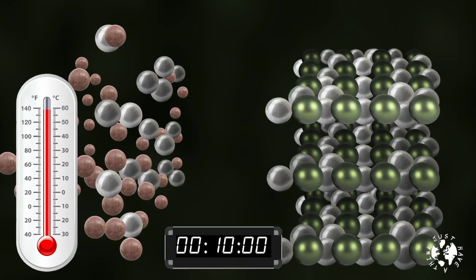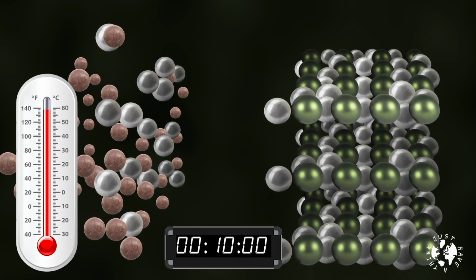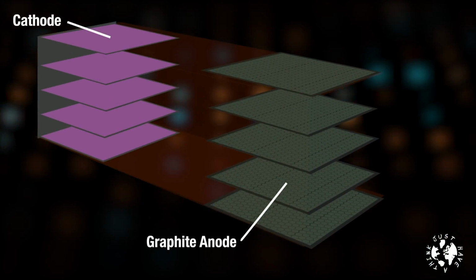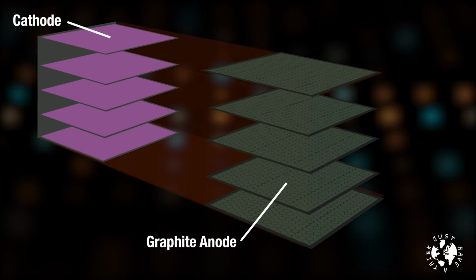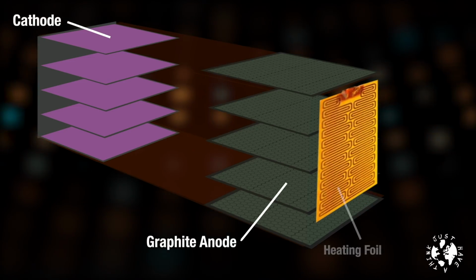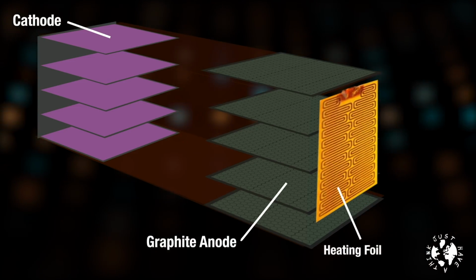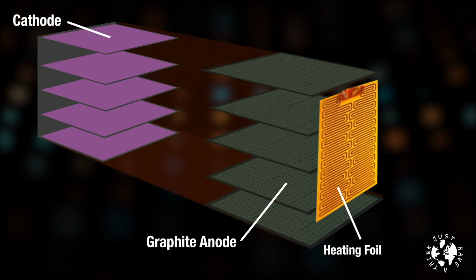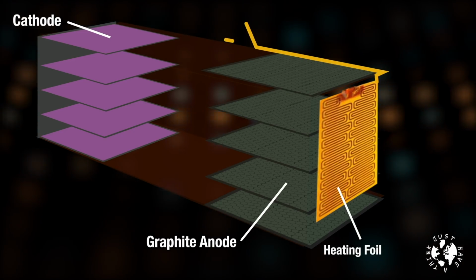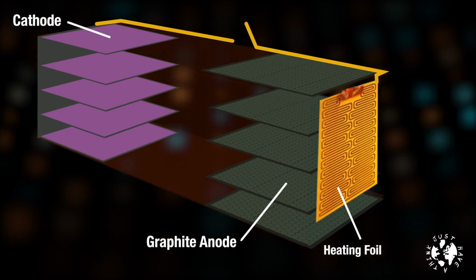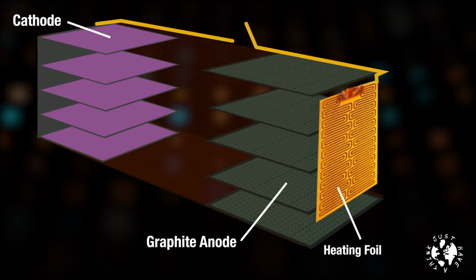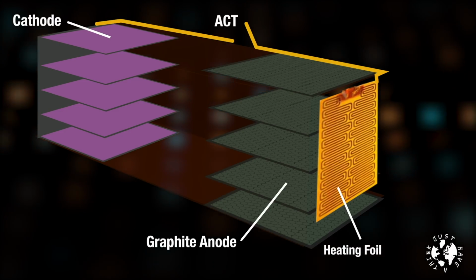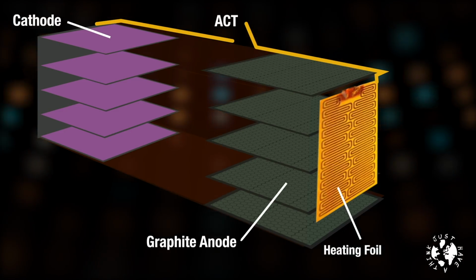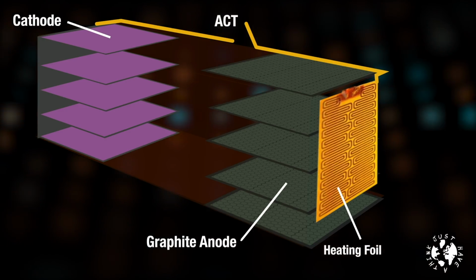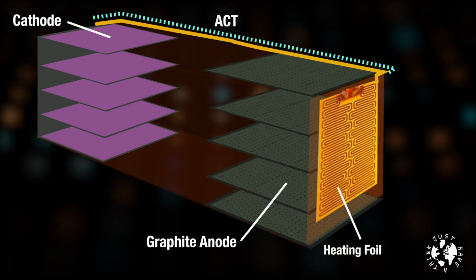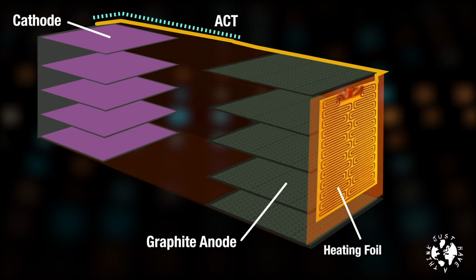The unique insight applied by Penn State is a self-heating lithium-ion battery structure, which embeds thin nickel foils inside a cell as internal heating elements. One end of the foils is welded with anode tabs and connected to the negative terminal, and the other end extends outside the cell to make a third terminal. The scientists call this the activation terminal because that means they get to use yet another acronym, the ACT terminal. This terminal is connected to the positive via a switch, and hey presto, you've got a flowing circuit with an input current coming in and heating up the foil.